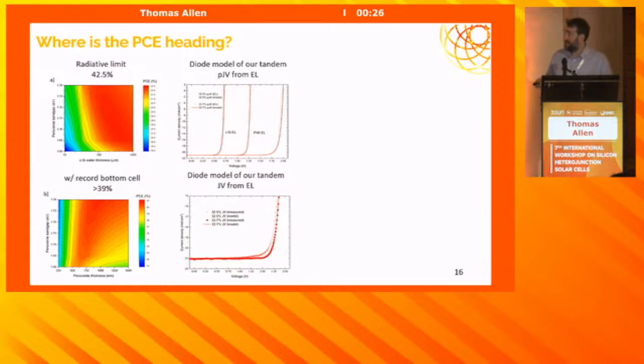Another interesting thing about this additive, this is comparing the JV curves very much zoomed in around the maximum power point. So we would always see this kind of slope in the JV that looks a little bit like a shunt, but it's not a shunt. It doesn't show up in the dark. So it's like a failure of superposition between the light and the dark JVs.